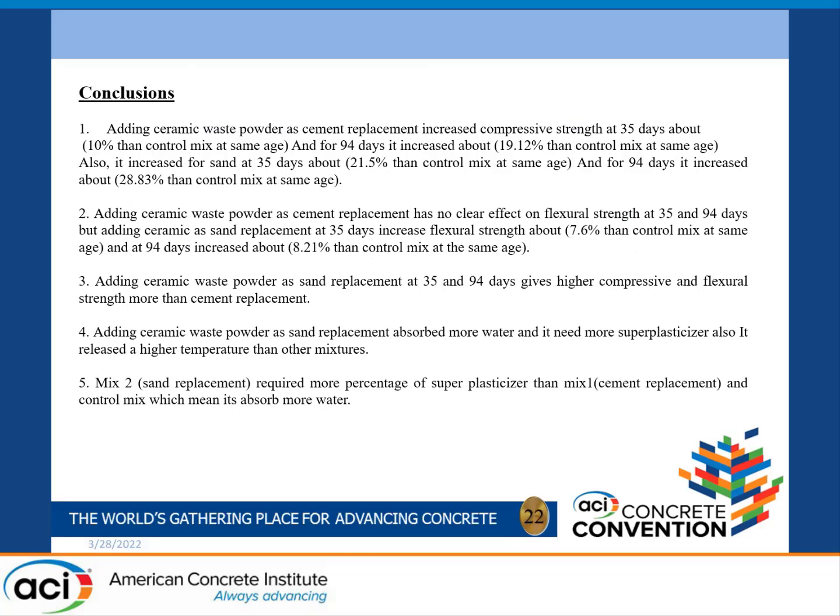Conclusion: adding ceramic waste powder as cement replacement increased compressive strength at 35 days about 10% over the control mix at the same age, and for 94 days it increased about 19.12% over the control mix at the same age. Also, for sand replacement it increased about 21.5% at 35 days over the control mix at the same age, and for 94 days it increased about 28%.